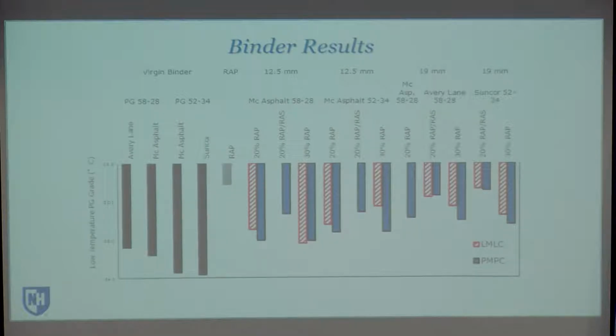We're seeing more of a change to warmer temperatures with the laboratory-produced mixtures than with the plant-produced mixtures. And actually, the other thing I wanted to point out with these mixtures is these Suncor materials. Those seem to be the worst in terms of the amount of change from what the grade should be, for both the laboratory and the plant-produced mixtures.